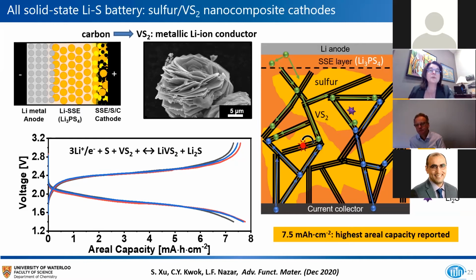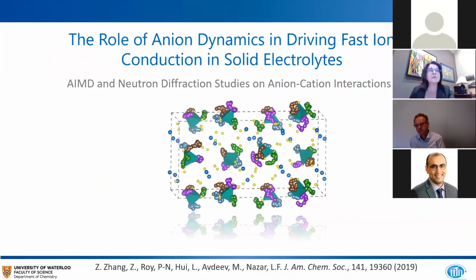So this cell was just used as a prototype, or sort of benchmark, for the material that I mentioned many slides ago now, the lithium thiophosphate. And what this did was make us think about why Li3PS4 worked well. As I said, its conductivity is only 10 to the minus 4, but we wanted to understand ion conductivity in these thiophosphates a little bit better. And so that drove us to some new adventures in understanding the role of anion dynamics in fast ion conduction. And in fact, our initial studies were on sodium ion materials.